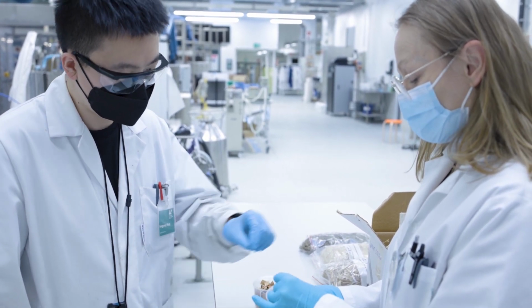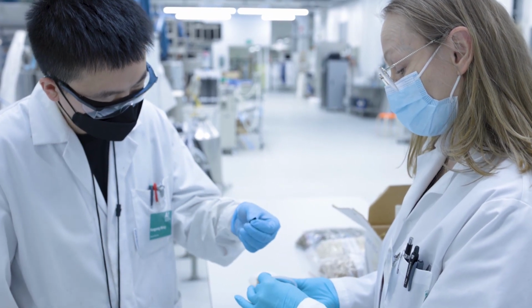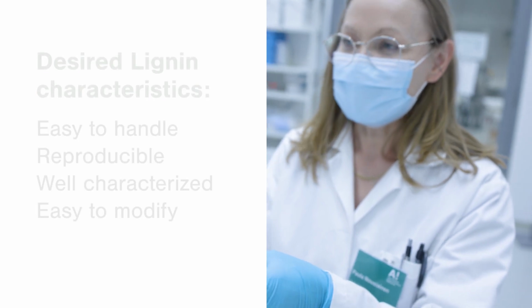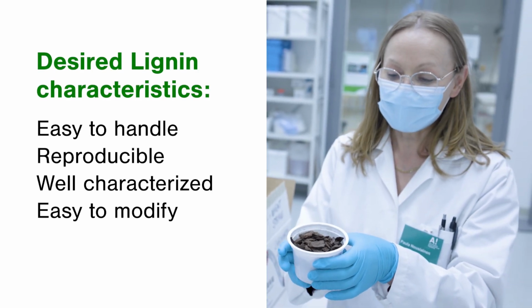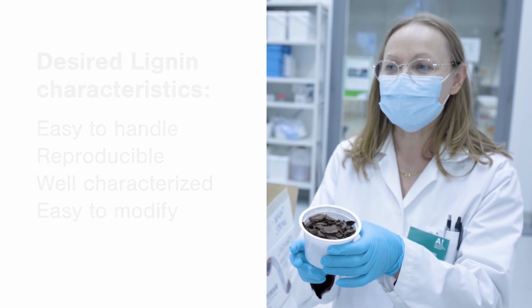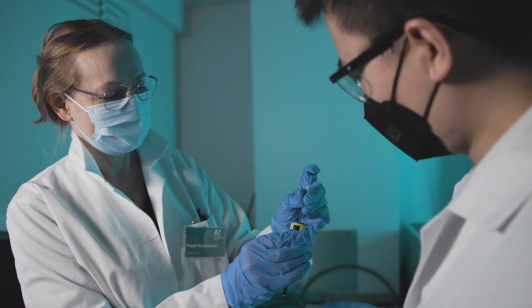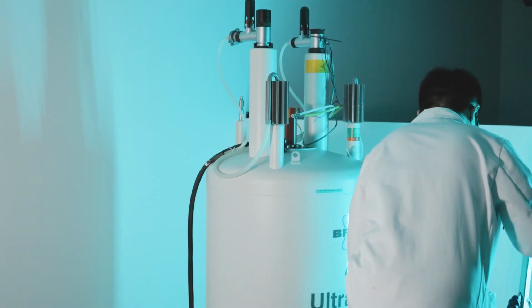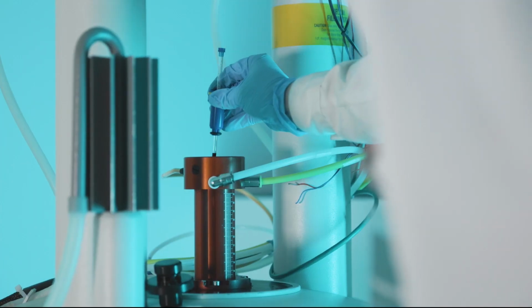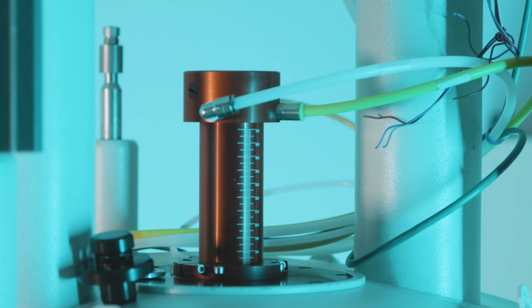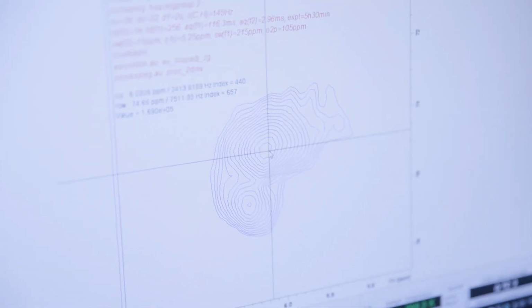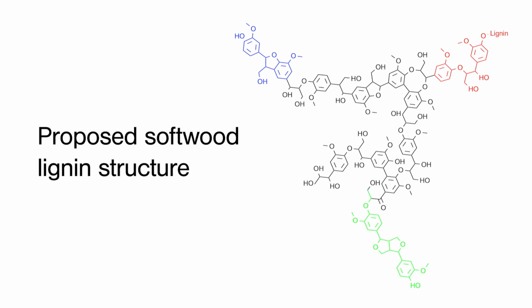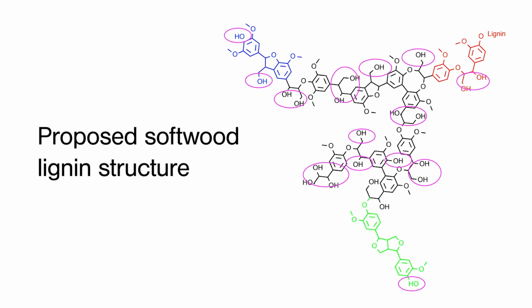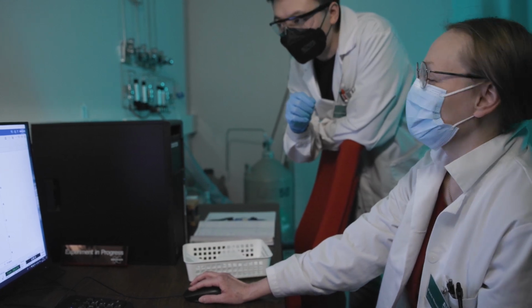The aim of the Aalto University Bioproduct Chemistry Group is to study the application of this lignin raw material for high-value materials. For optimal performance in applications, the lignin should ideally be easy to handle, reproducible, well-characterized, and easy to modify. At Aalto, we first analyzed the lignin batches produced by Avantium by using spectroscopic methods, for example NMR spectroscopy and gel permeation chromatography. Here, the sample is placed in a high magnetic field NMR, and in this way information can be obtained of the macromolecular structure of the lignin polymer, such as interconnecting bonds and the amount of reactive hydroxyl groups. These techniques give us a deeper understanding of lignin structural properties and its reactivity for further modification and application possibilities.